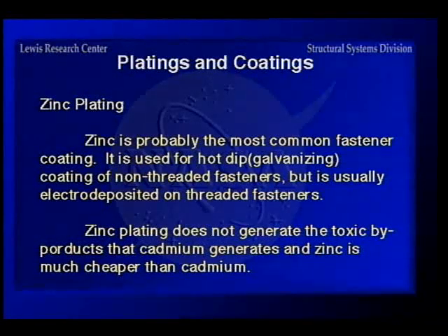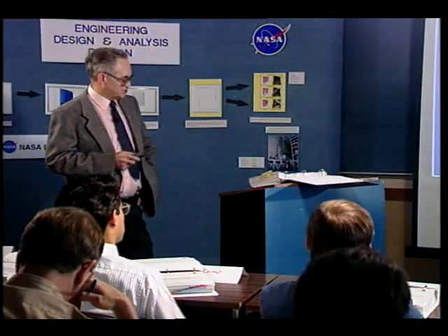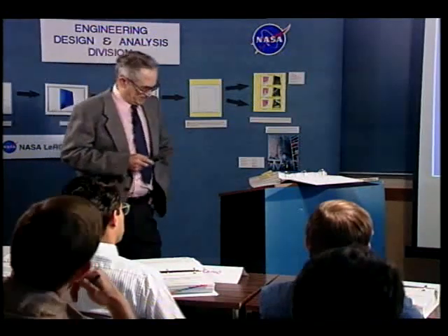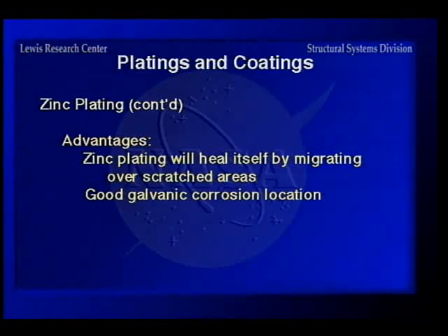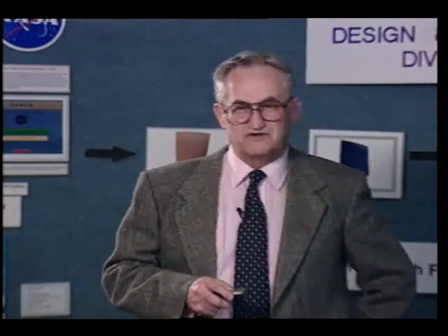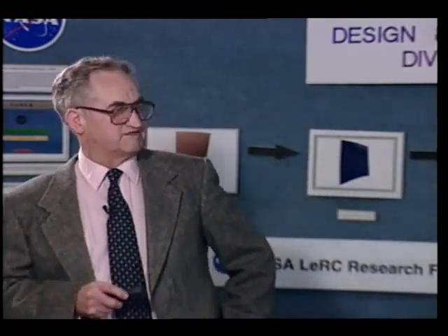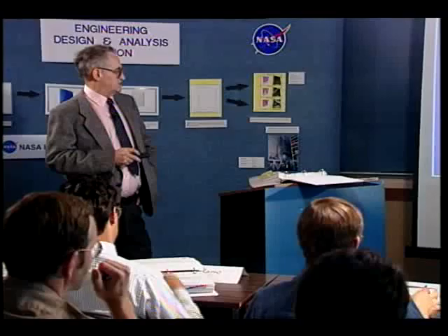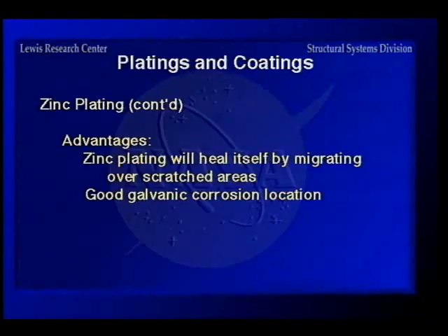But it will heal itself over by migrating over scratched areas. If you scratch an area, in fact, down at the Cape, they did a study on how far zinc would migrate, and it would go over a scratch about 1/8 of an inch wide and go back and heal. It will kind of heal itself to a certain extent. And it has a good galvanic location, but it's not as good as cadmium for corrosion resistance.